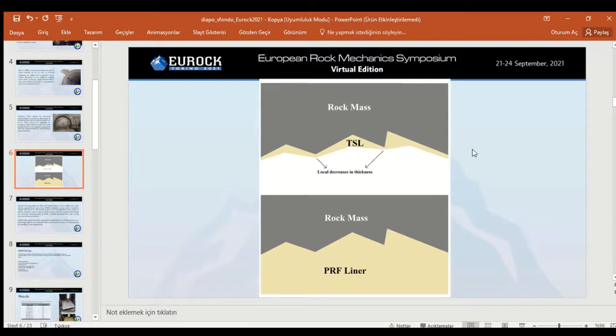As another problem of TSLs, spraying on rough surfaces may cause local decreases and significant change in the thin liner thicknesses. Therefore, TSL load-bearing capacity can be notably affected as a result of the uncontrollable inhomogeneity in the liner thickness.